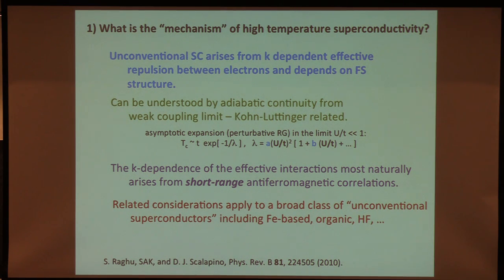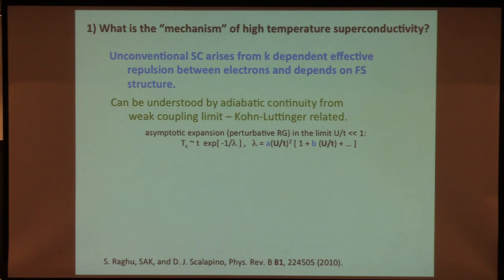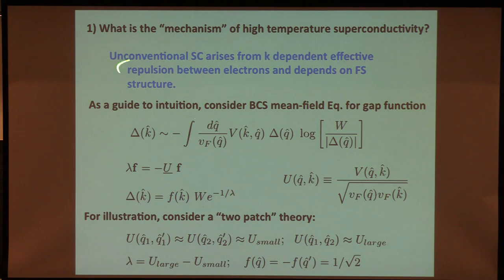Yes? What is it that changes as the antiferromagnetic correlations get long range? Yeah, so it depends on the range of the correlation. There are a number of things. One is superconductivity ultimately is an integral over the whole Fermi surface. So if this interaction is very highly peaked, that's actually very inefficient. It means you only get pairing from a couple of points on the Fermi surface, a couple of hot points. So you want to have U large bigger than U small, but ideally you would like it spread out over a large range of K.